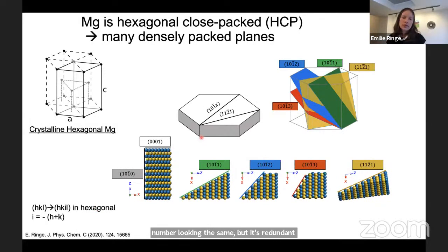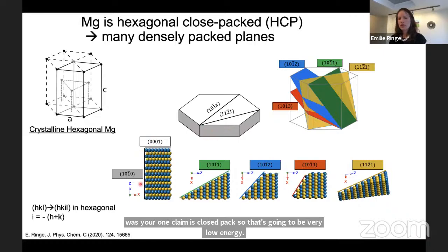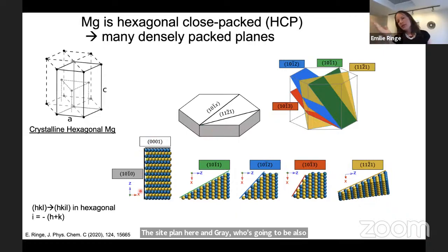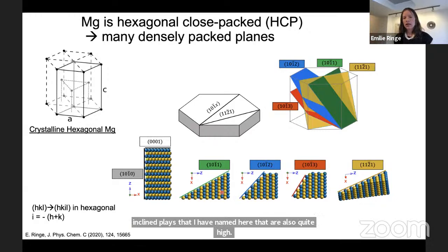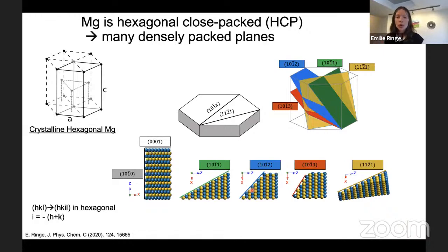So if we look at that, the basal plane, the 0001 plane, is close packed, so that's going to be very low energy. The side plane here in gray is going to be also pretty low energy. And then there's a number of inclined planes that I have named here that are also quite high density and low energy, and these are capable of being twin planes in the HCP systems. They are known to be twin planes in the HCP system.